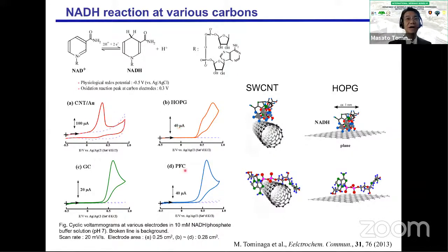HOPG, plastic formed carbon, and glassy carbon. The important point is this is our carbon nanotubes. The important point is that carbon nanotubes and HOPG are also sp2 carbon. HOPG has no defects and a very flat surface. At this single wall carbon nanotube surface, we observed the oxidation reaction started from 0 volt, right? On the other hand, at the HOPG, this reaction started from around 0.3 volt, quite different.